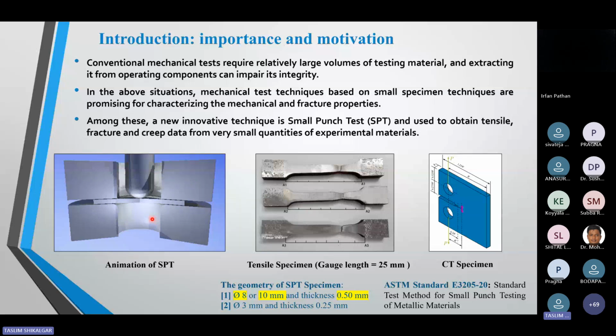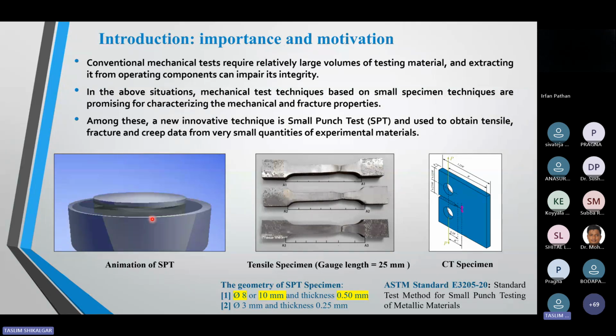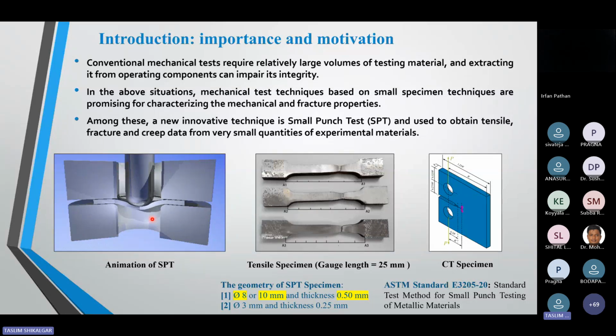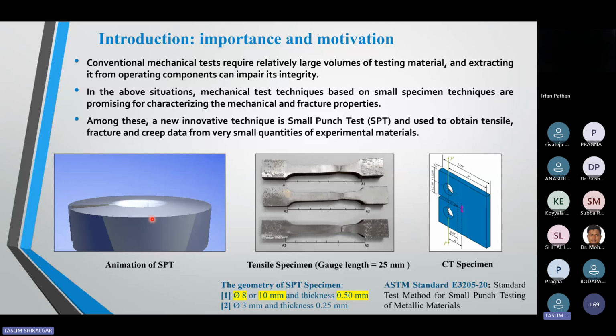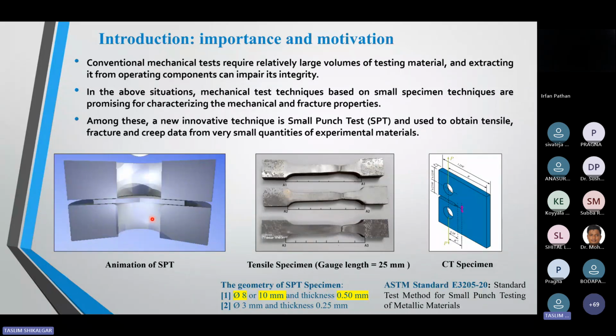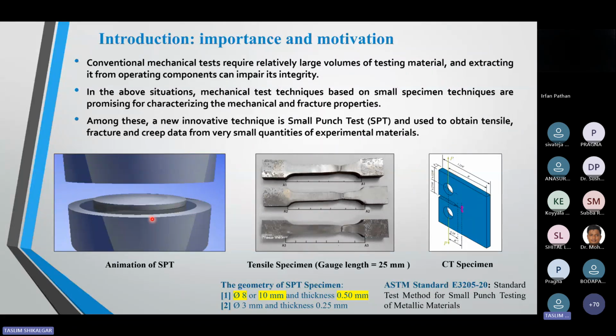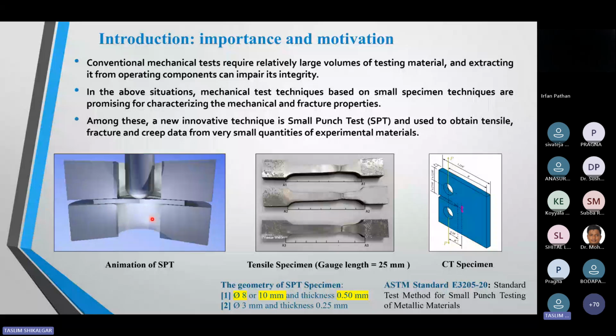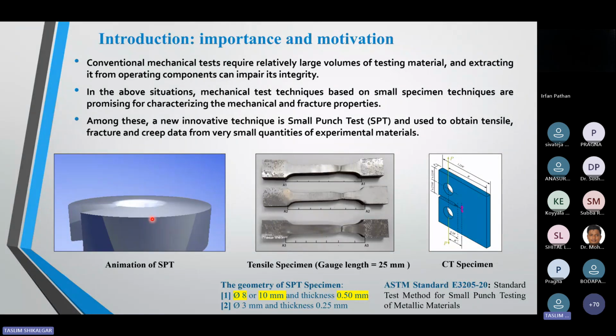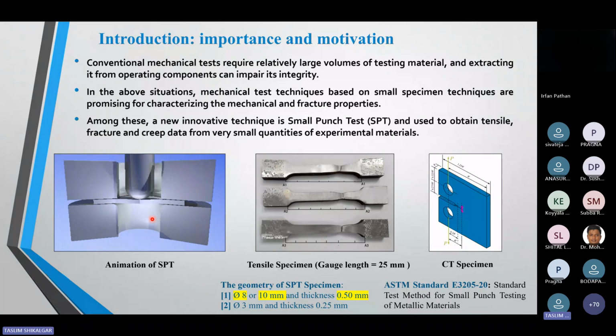Almost all nuclear industries are using this type of specimens. Recently in 2020, ASTM observed that the nuclear industry developed this approach and is using it, so they decided to generate one ASTM standard for this specimen. So anyone in the world can use that ASTM standard to test this type of specimens. How these specimens can be fabricated, what dimensions are needed for the upper die, lower die, and the punch. So they made this one standard, so each and every person can use similar fixtures, similar punch, and similar specimen dimensions to extract the fracture as well as mechanical properties from this type of specimens.